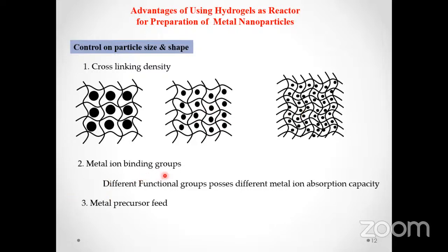Second is the metal ion binding groups. If we use different functional groups in the polymeric hydrogels and we don't change the cross-linking density, then again we can control the particle size of the metal nanoparticles, because different functional groups have different binding ability towards different metal ions. So by variation in the functional groups which are responsible for the absorption of metal ions in the hydrogel structure, the particle size of the metal nanoparticles can also be controlled. And finally, the metal precursor feed is also an important parameter. If we have a lower feed, then each mesh will have a lower amount of the precursors, and it will result in a relatively smaller metal nanoparticle. And if we increase the feed of the precursors, then each mesh will have a larger amount of the metal precursors, and that will result in the formation of larger particles.